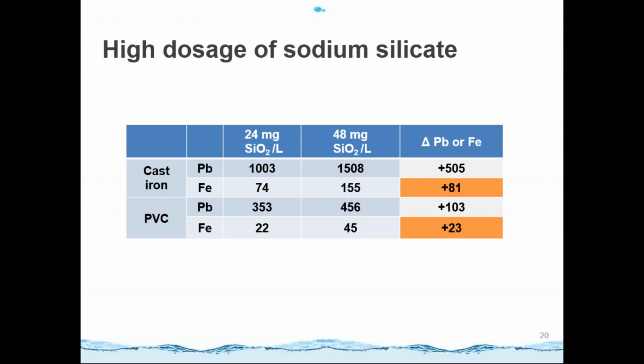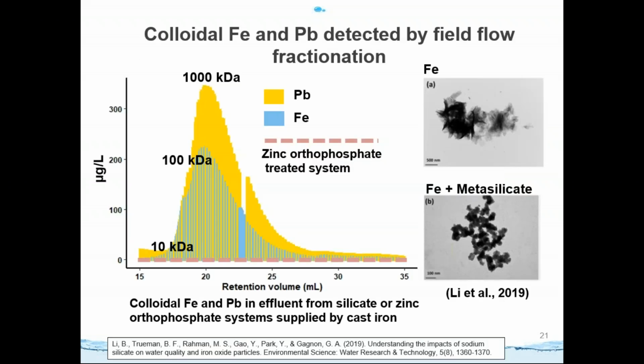So we suppose that the dispersion of the colloidal matter from the corrosion scale and the deposit in the pipe loop system is the reason for the increase in lead and iron. So we used another tool called field flow fractionation. Field flow fractionation can separate the matter depending on particle size. So it can separate the dissolved lead and the colloidal lead or the particulate lead.